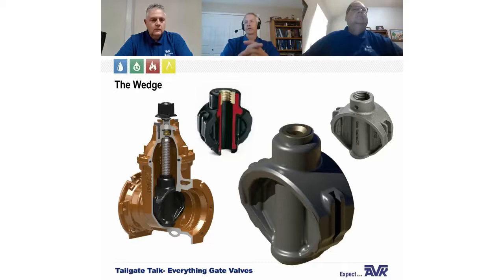And another thing that we should say about the gate valve wedge is we do offer NBR and EPDM, and the vulcanization system that bonds the rubber to the ductile iron is proprietary to AVK. We blast it, coat it with 2 primers, and then we vulcanize it. And the EPDM we use for potable water. NBR has a couple of applications for us. One is anything that has hydrocarbons or something of that nature. I'm sure it would be applicable for other things as well.